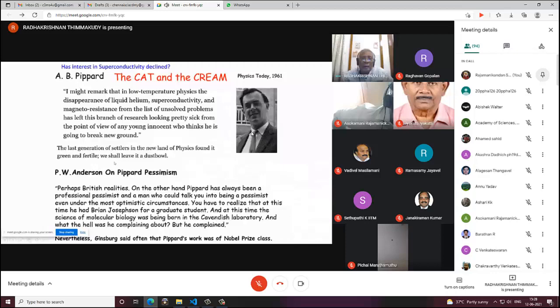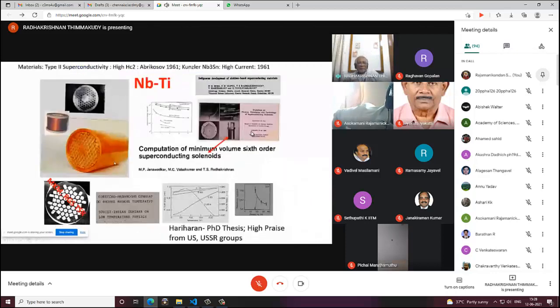Okay. Now, the only other thing that continued was two areas. One is that I didn't mention that superconductors also had an energy gap. Specific heat experiments told you that after that Tc, there's a jump in specific heat that exponentially went down to a low value tending to zero, and that is a second order transition, and that was later attributed to an energy gap in superconductors. Many experiments have shown the energy gap in superconductors. And then the research on using these materials in magnets continued.